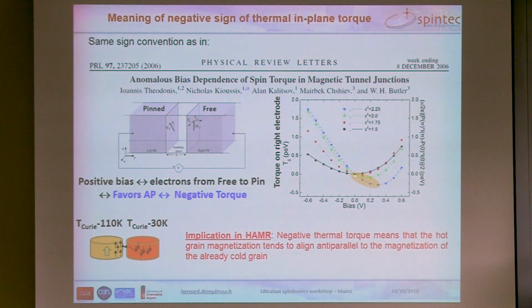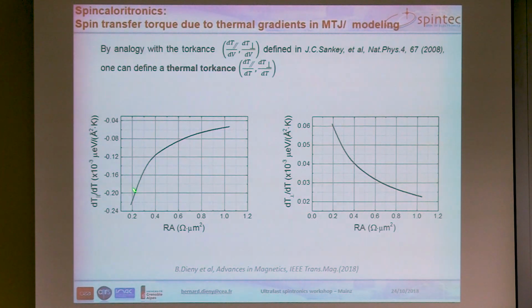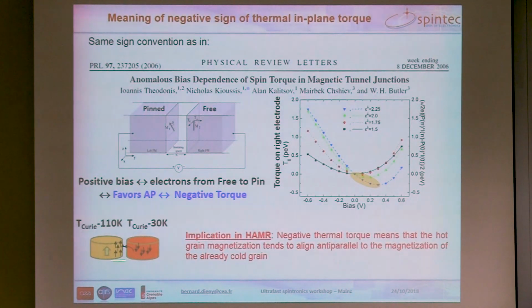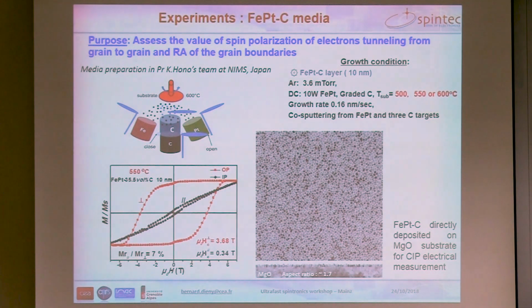And this corresponded here, positive bias, to negative torques. And so it means that negative torque corresponds to favoring antiparallel alignment. So this is what I explained. We found here negative torques, and so negative torque indeed favors antiparallel alignment between the hot grain and the already cool grain. So now there was a very important parameter in this theory, which is the polarization of the electrons